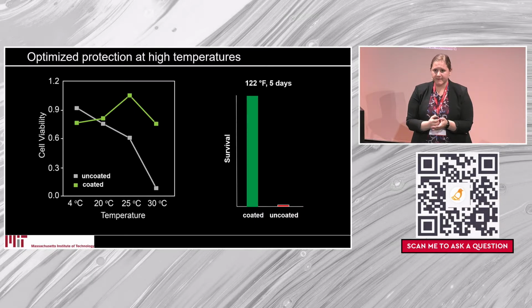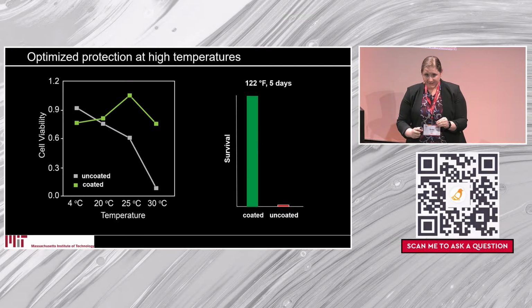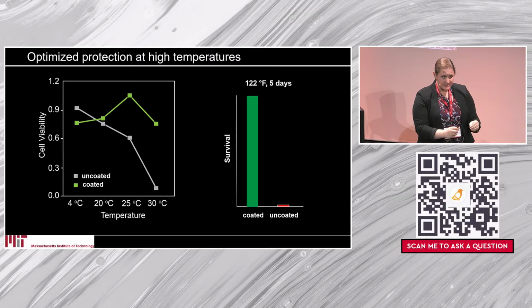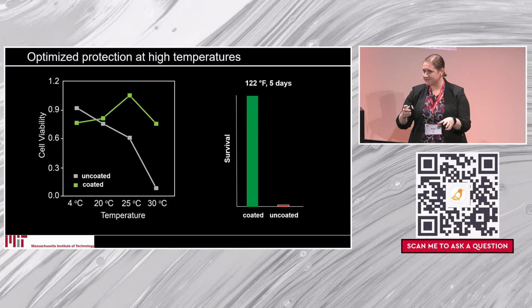So on the left here, we can see cell viability as a function of temperature. For our uncoated cells, anything above refrigeration kills them. For our coated cells, we can show that they survive with nearly equivalent viability up to 30 degrees Celsius. But more importantly, we can stick these in an oven at 50 degrees Celsius, which is 122 degrees Fahrenheit, for 5 days, and we have cells survive. That's a temperature that can cook an egg.